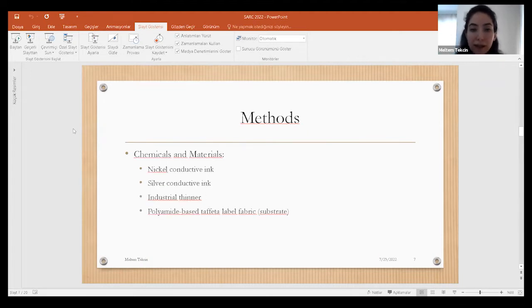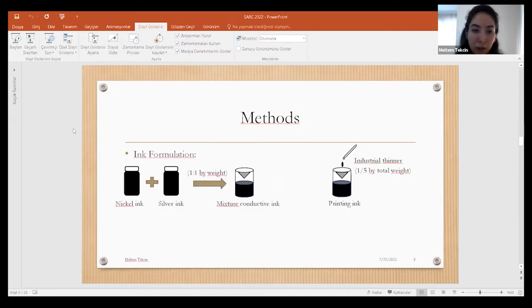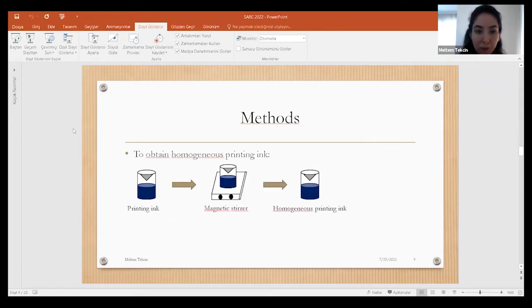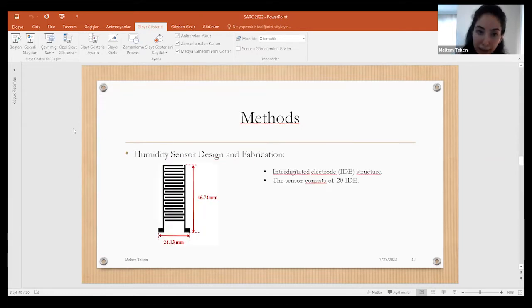Chemicals and materials: nickel conducting ink, silver conducting ink, industrial thinner, and polyamide-based label fabric were used in the study. Ink formulation: nickel ink and silver ink were added into a beaker, then industrial thinner was added into the mixture, and the printing ink was stirred on a magnetic stirrer in order to obtain homogeneous printing ink.